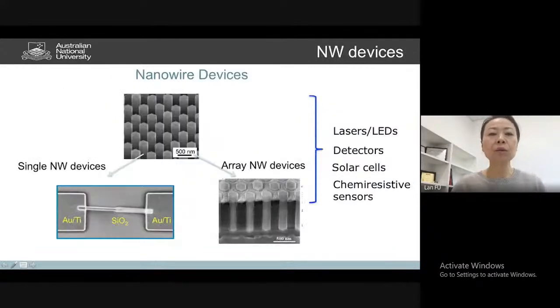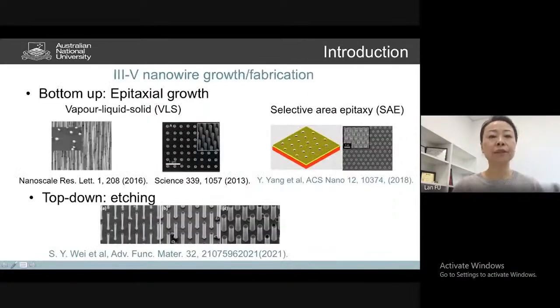That's what we do. So once we have a nice nanowire array fabricated, one thing I have to mention is that if you're spraying metal particles randomly, of course you will have a lot of non-uniform nanowire growth, because when the precursor atoms come down, because of the non-uniform dispersion of your metal particles, you won't be able to control their position. Thereby, your nanowire material after growth will not be uniform in terms of height, diameter, and spacing. Using this positionally controlled way by doing nanolithography, you can fabricate this highly ordered nanowire array. Thereby, you have more ability to design the optical and electrical properties. So that's the approach we're taking.